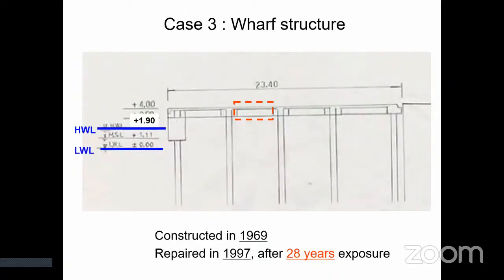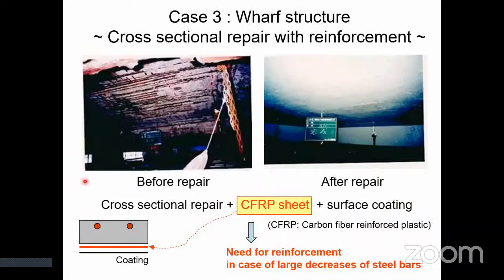This is case 3. High water level is around here. This structure was constructed in 1969 and repaired in 1997, after 28 years of exposure. In this deteriorated part, after cross-sectional repair, a carbon fiber reinforced plastic sheet was attached for reinforcement because of a large decrease of steel bars. And afterward, surface coating was applied on the CFRP sheet, like this.